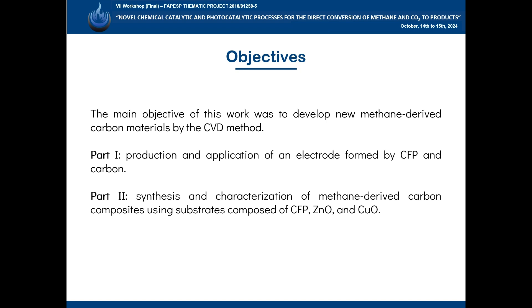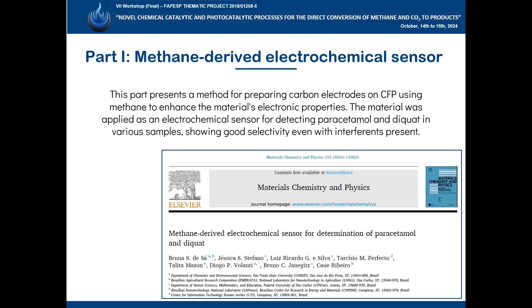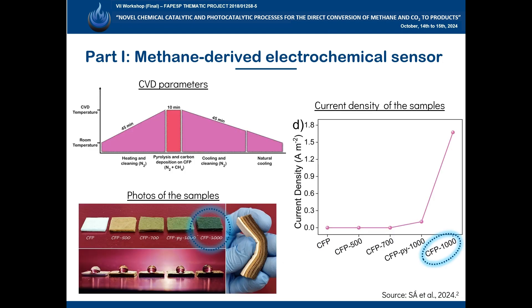So, in this work, we developed novel methane-derived carbon materials by the CVD method. In the first part, we demonstrate a method to prepare carbon electrodes on CFP using methane to improve the electronic properties of the material. Various synthesis temperatures were tested, and the sample produced at 1,000 degrees Celsius proved to be electrically conductive.